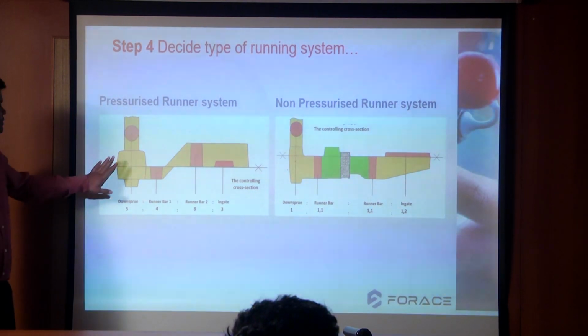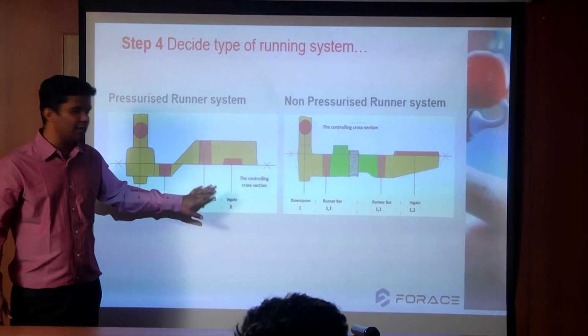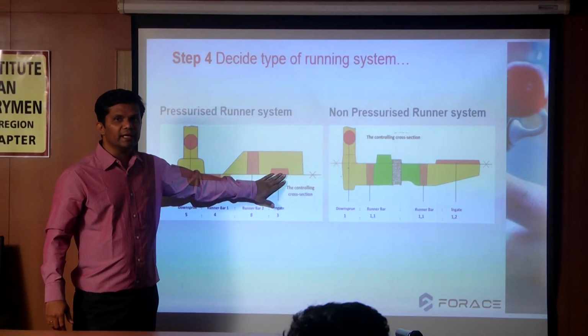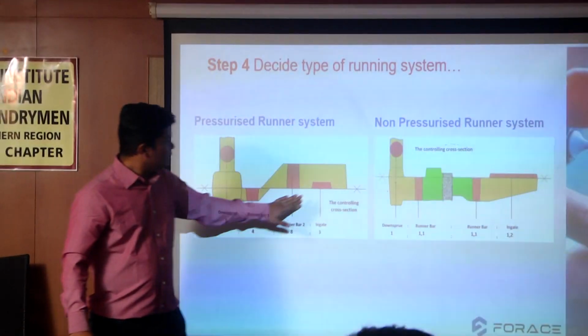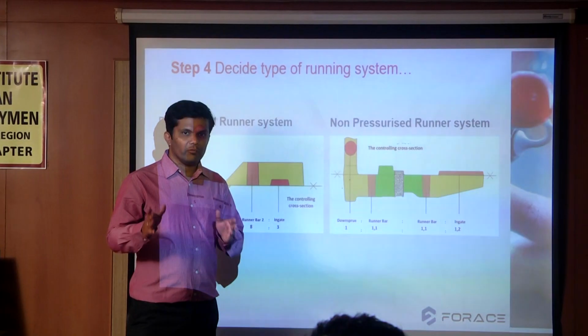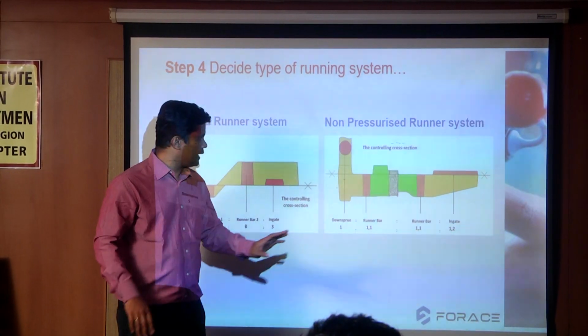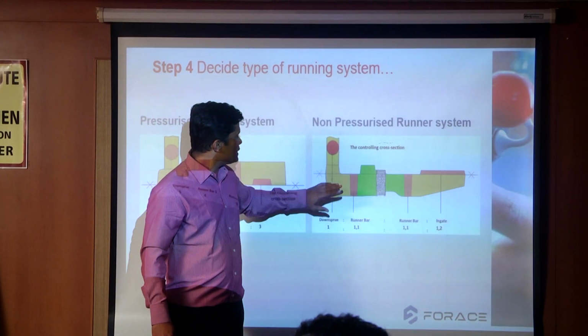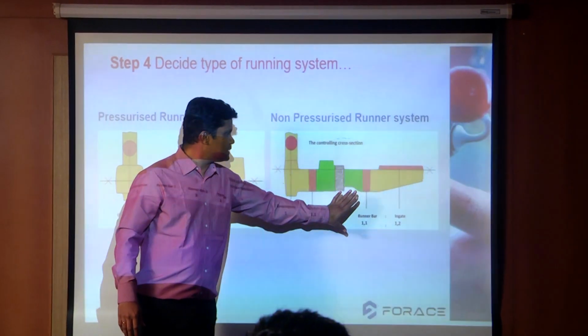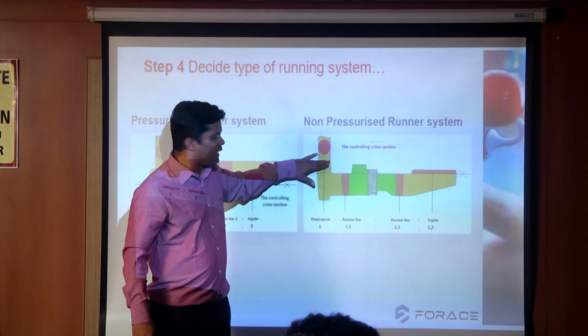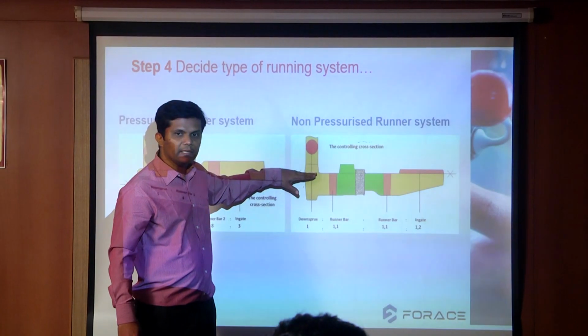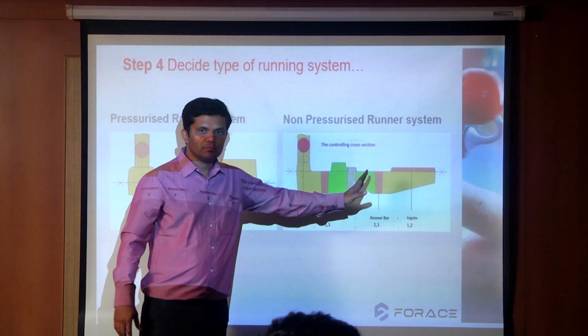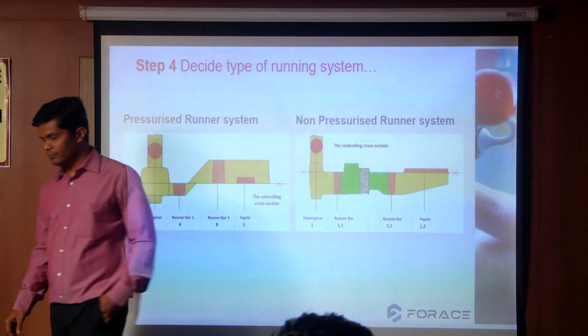The difference between both is that in a pressurized system, the controlling area, the choke area we have calculated, will be at the inlets. And these inlets will control the velocities as well as the pouring time of the system. But in a non-pressurized system, the area goes on increasing. The choke area will be at the downsprue or very near to the parting line. Then the area is increasing.